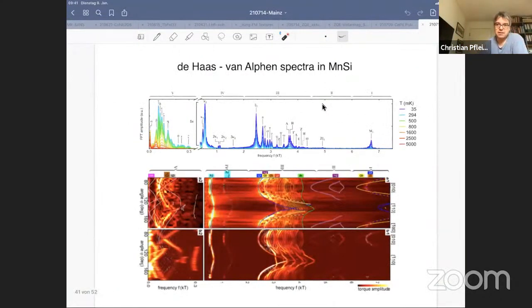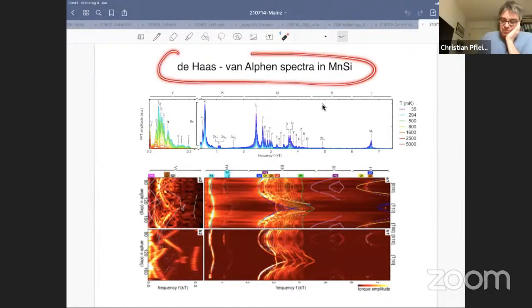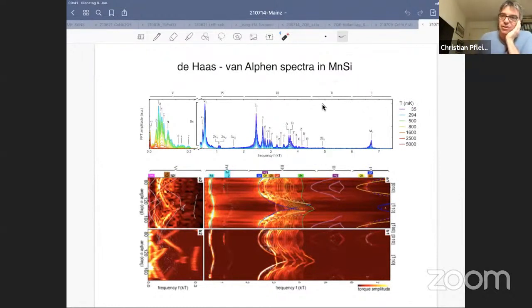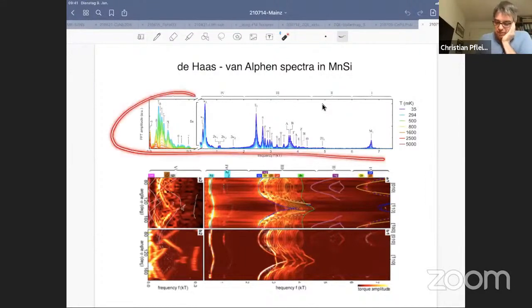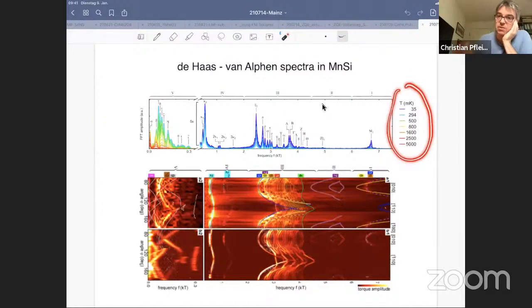Okay, now all hell breaks loose. So Mark and some of the students measured the de Haas-van Alphen effect in MnSi. And you don't get just 2 frequencies or 3 or 4, but you get a nice and even 40. So these are the spectra. These are measurements that go down to 35 millikelvin. So these are the oscillation frequencies. They show strong temperature dependence because they have different effective masses.